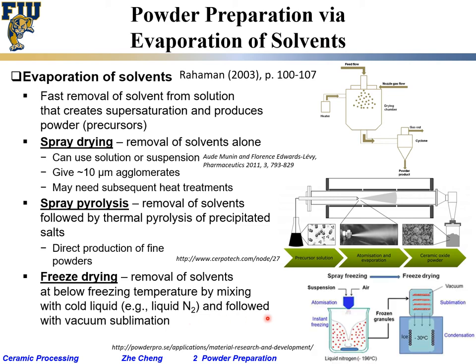In the freeze drying setup, you have the suspension, and quite often liquid nitrogen. You spray the suspension into the liquid nitrogen and they form frozen granules — the water or organic solvent becomes frozen. The granules are agglomerates or very fine powder bonded together, quite often into 10 micron particulates.